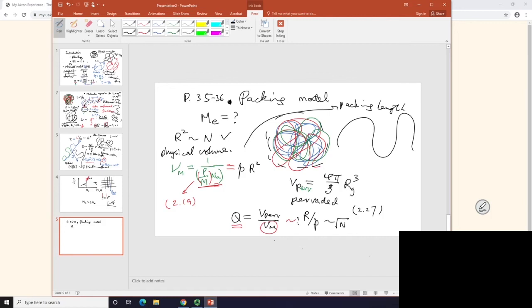The concept of minimum molecular weight for entanglement. I know that I wrote down this, but in literature, this is called entanglement molecular weight, called ME, which is connected to what I said about the tube getting shorter and shorter until the tube is as long as the tube diameter.